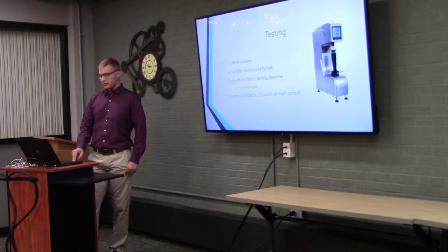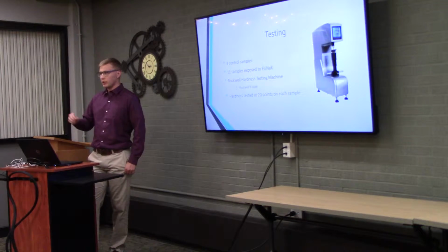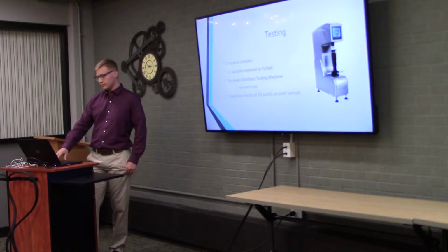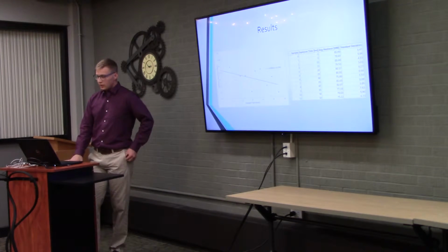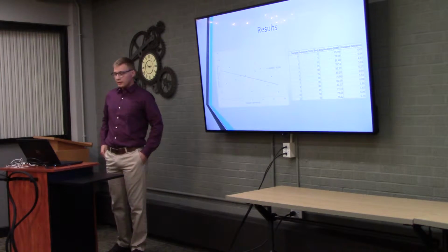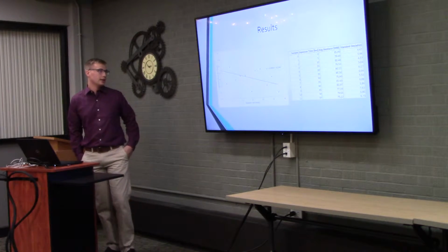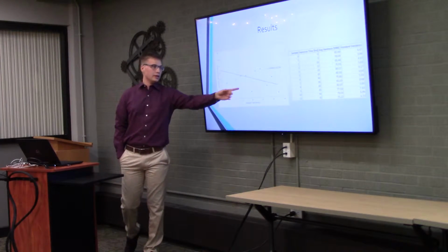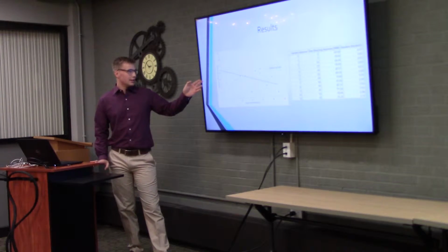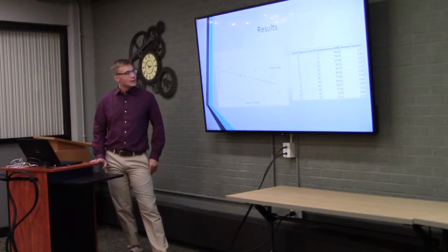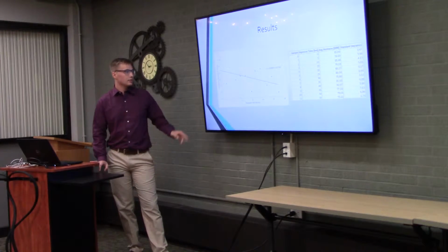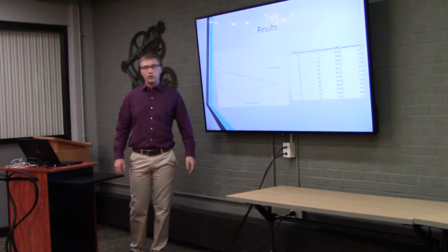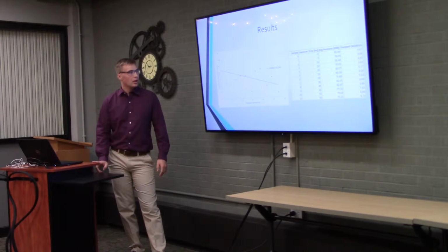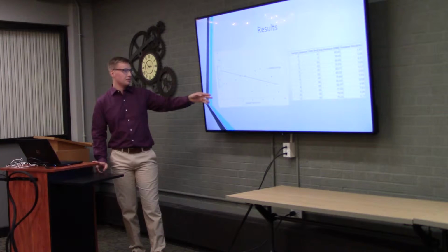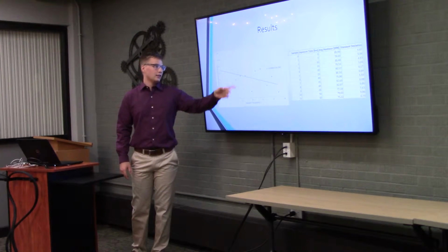And the hardness was tested at roughly the same 20 locations on each sample, so that you would get a good average hardness of each sample. And these are the results that I got from that. The first thing that you can see is this linear trend line. It has a distinctly negative slope, which indicates that the hardness did decrease over the 55-hour exposure time. And you can see, however, that the data is kind of scattered.